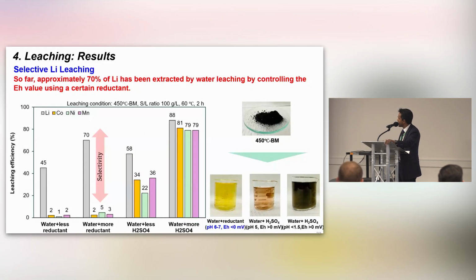Now I will talk about some selective leaching results. This is the result of selective lithium leaching. In this test, we used the black mass thermally treated at 450 degrees. Here we basically use water as our lixiviant. But the most important point for the lithium selective leaching is that we can control the ORP by introducing some reductant with the main lixiviant. If you remember the Pourbaix diagram related to lithium, if we decrease the ORP value under a certain level, we can dissolve lithium as lithium ion. So here, with some reductant and the water, we could achieve more than 70% of lithium, while the other critical metals mostly remain in the leach residue.